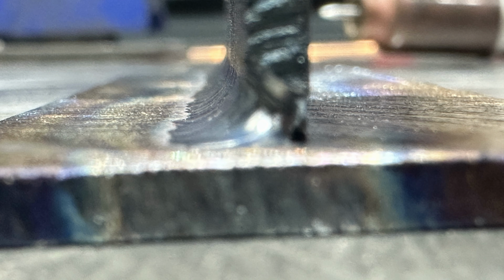Here's another photo of the same weld, and you can see very concave, and due to the tungsten angle not hitting the root at a 45, it more or less is slumped down on the bottom plate. Everything else is looking pretty consistent. The toe line isn't too bad, but simply holding a little bit too long of an arc and not pushing enough filler really kind of screwed up our throat depth of the weld. So be aware of that, pay attention to it, and if in doubt, cut your material in half and visually look at it. Well, let's go back to making mistakes now.